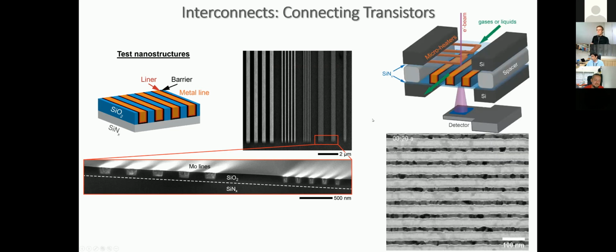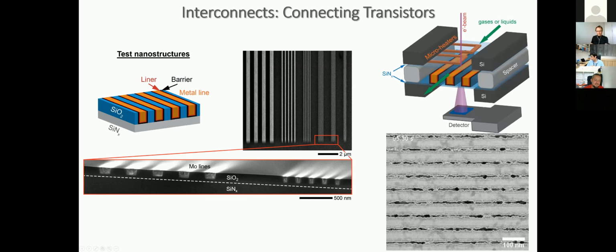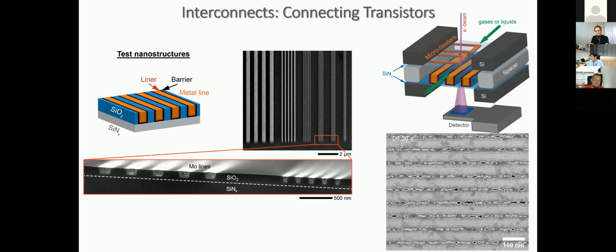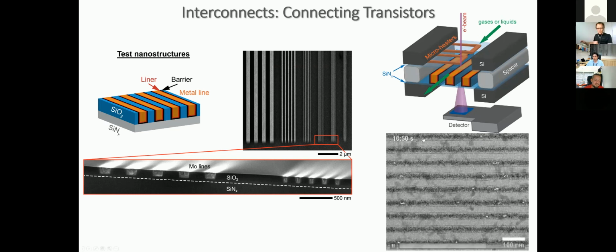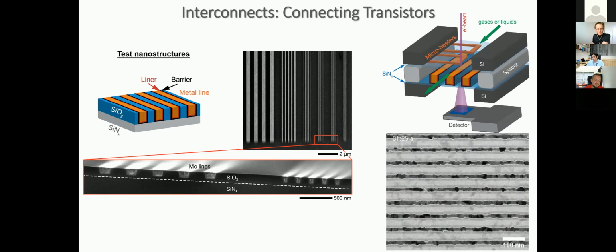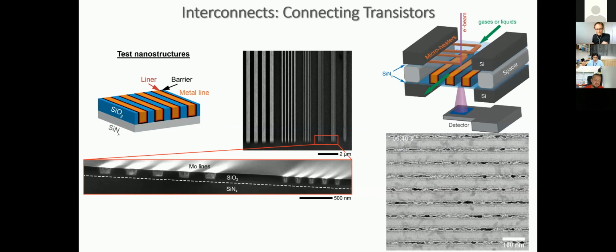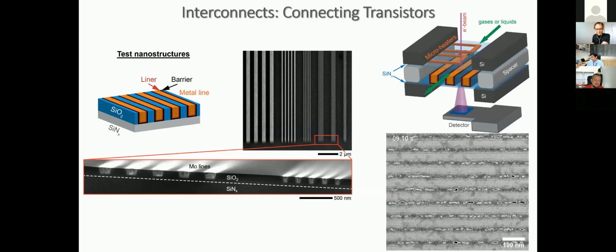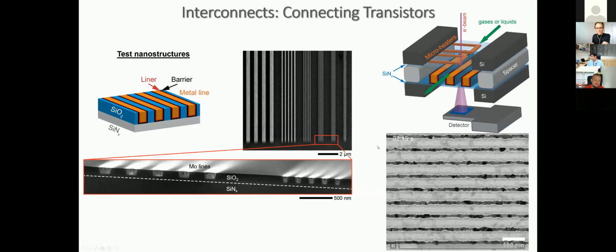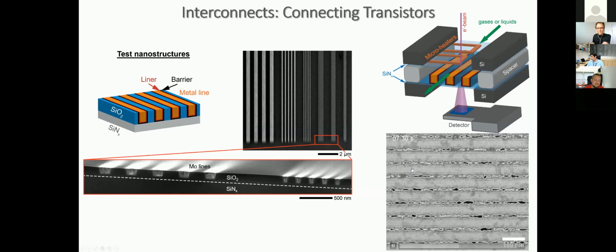Okay, so our goal is that we can actually integrate this into our liquid cell. This is a very recent result that my postdoc Ifan took. What you see here is etching of the metal line. We've all seen etching of metal nanoparticles, with different facets etched differently and so on. But now we're patterning things that are crystalline. Here the crystallinity is not controlled. What we're going to do in the future is anneal, see how crystallinity changes, and then see how, depending on the annealing conditions, the etching changes. But again, this is your typical nanoparticle, only patterned, and these are nanowires microns to centimeters long.